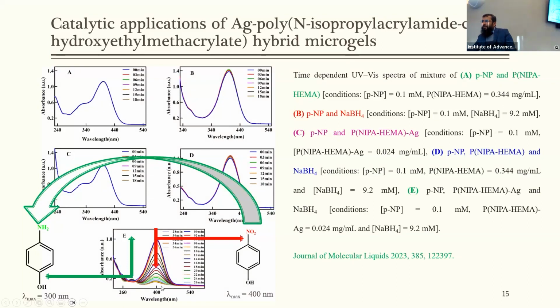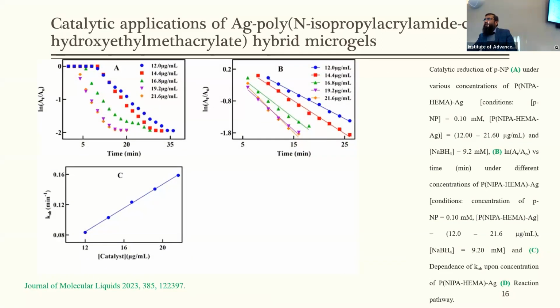The absorbance at 400 nanometers, associated with p-nitrophenol, was measured as a function of time to monitor the progress of the reaction. We carried out the catalytic reduction under various concentrations of the catalyst. We used a pseudo first order kinetic model for determination of the rate constant. For this purpose, log of At over A naught was plotted as a function of time. It was noted that initially log of At over A naught remains constant, then decreases linearly with time, and again becomes constant.